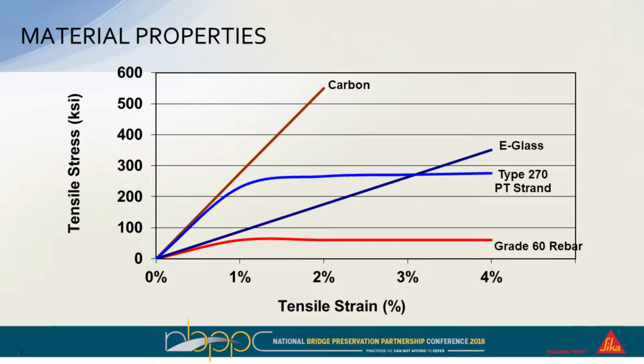So this slide just illustrates the comparison of some of the use of FRP materials with the conventional types of reinforcing steel or post-tensioning strands. Important to note, these material properties, at least for the carbon fiber and the glass fiber, are just the fiber properties, so it's not the cured laminate properties. But the point here is that we can use materials that have a much higher tensile capacity when compared with conventional steel, but also allow us to optimize the strength of these types of materials.